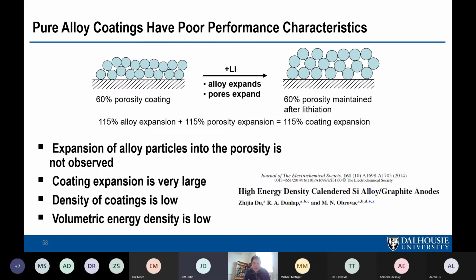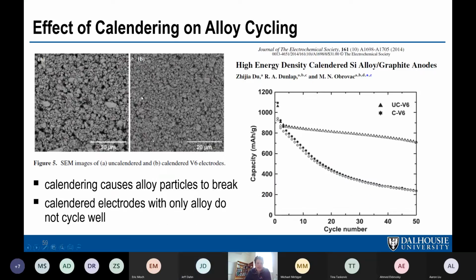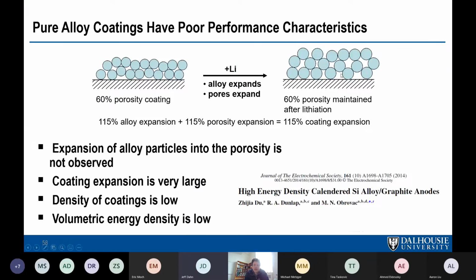But like I said, calendaring to reduce the porosity takes gigapascal force. You can calender at nip pressures in the gigapascals. You're never going to reach that in a cell, even in megapascals, which is still ridiculously high. The separator is going to crush before you do this. This is orders of magnitude higher pressure than what's typically in the cell, which is 15 to 20 psi, maybe 40 psi stack pressure. It's not even close. This would crush the separator without even knowing it was there.